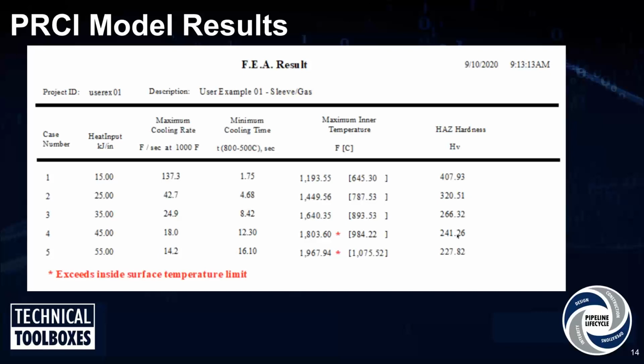So that's the temperature that you have to monitor to predict or mitigate your risk of burning through. The model was set up that for low hydrogen and cellulosic electrodes, if you exceed that 1800 or that 1400 value limit, you have a red asterisk that pops up to say, hey, in this case, at 45 kilojoules an inch, you're going to be risking burning through.